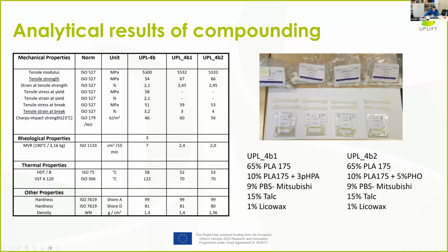And you see here also the Young's modulus remains, in one case it's getting a little bit higher. Here it stays the same, but the main result is that in comparison, the materials don't impact the compound properties. One thing that was not so good for us was the melt volume rate here, because we go from an injection type material to an extrusion type. So the material is getting harder to process. So it took much more time to use this material in the injection molding. We have also to test this material, but you can see here, we have to see if this will be working.